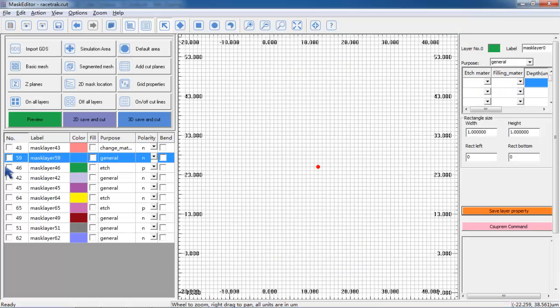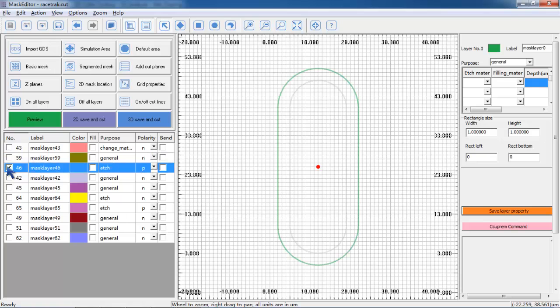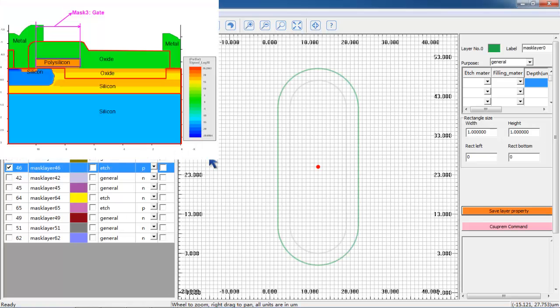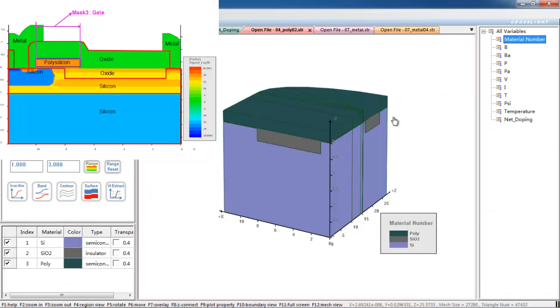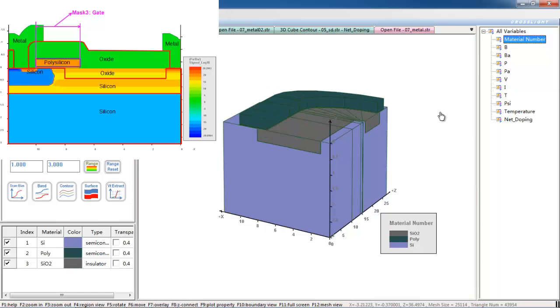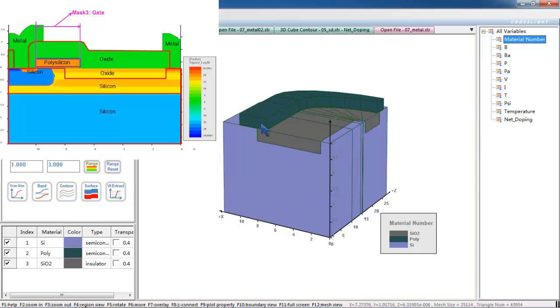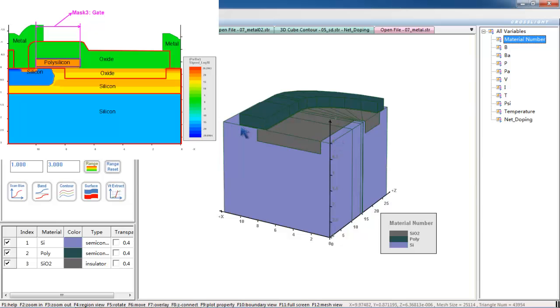The next mask layer is used to process the polysilicon and oxide layer. Before this mask step, we need to grow a thin oxide layer as gate oxide. Then we deposit polysilicon. Then we use this mask layer to etch the polysilicon and the thin gate oxide below. Careful with the depth of the etch so that the deeper oxide will remain as oxide isolation.